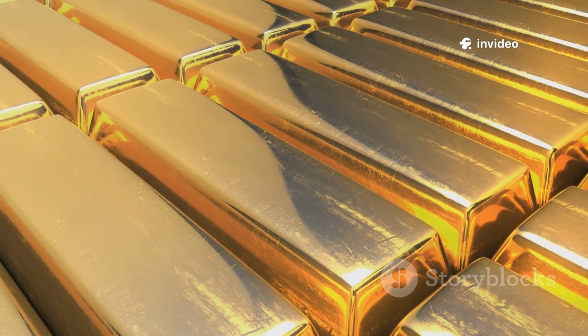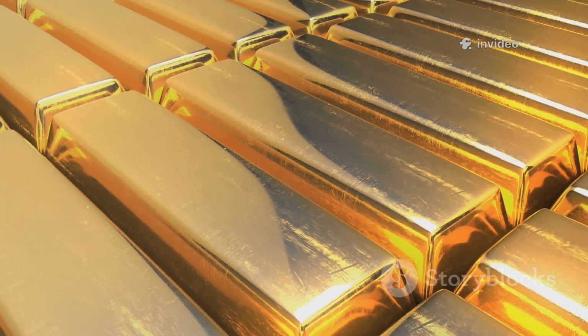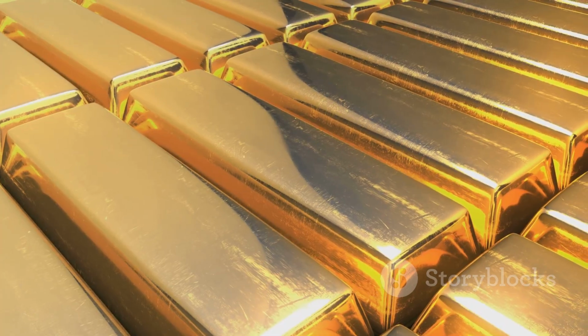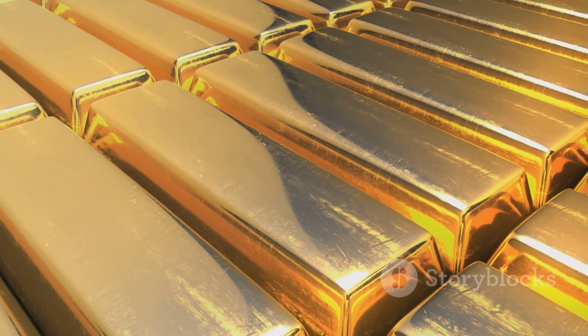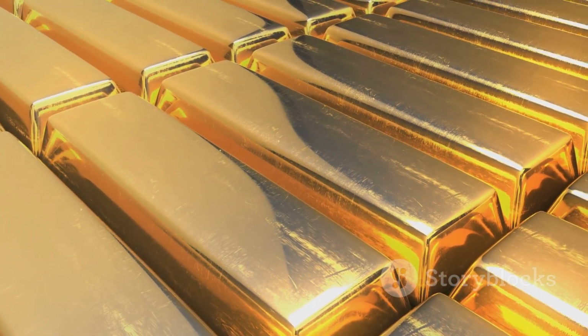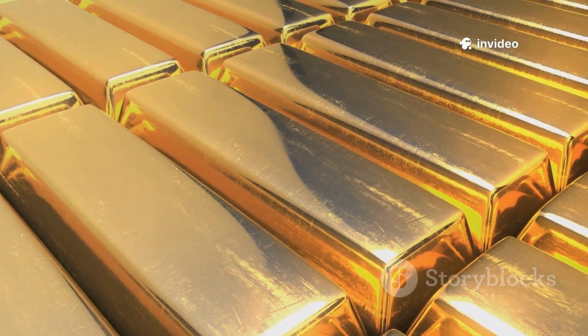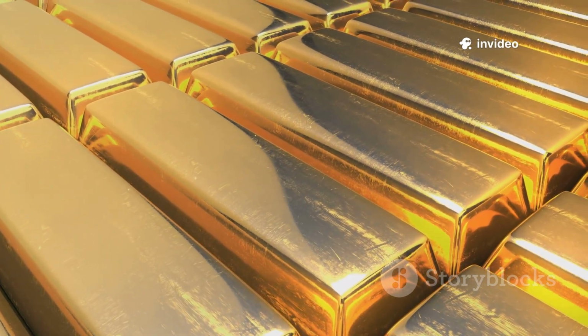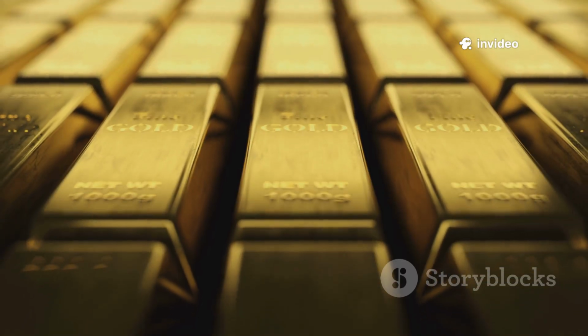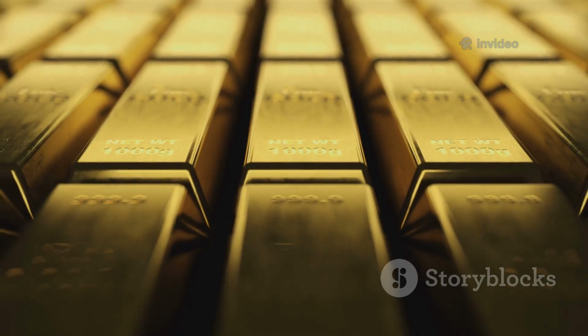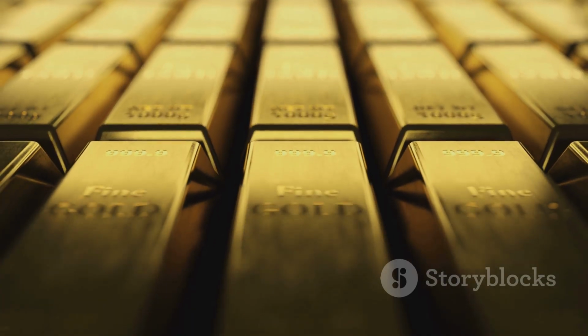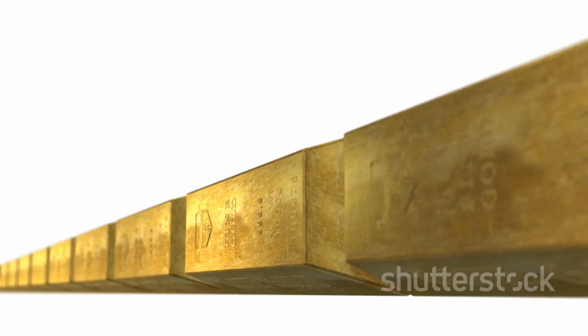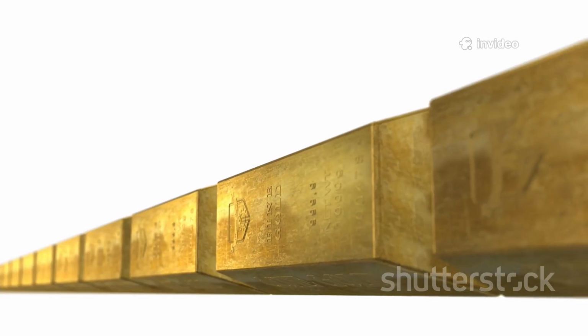If it cools too quickly, it can crack or develop internal stresses. If it cools too slowly, the crystal structure of the gold can be imperfect. The cooling process is managed carefully, sometimes with water jets, to ensure a solid, stable bar. While casting is common for large bars, smaller bars, especially those prized for their perfect finish, are often made differently. This method involves minting, similar to how coins are made.